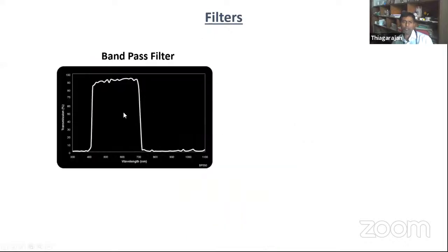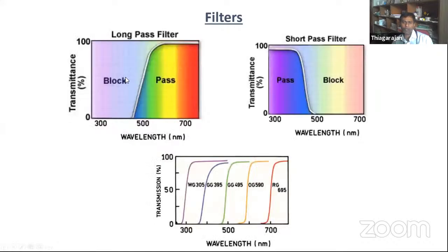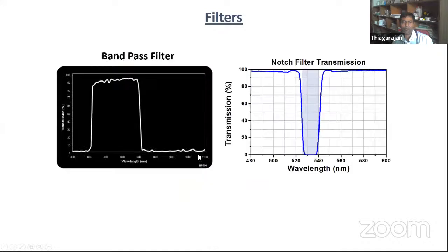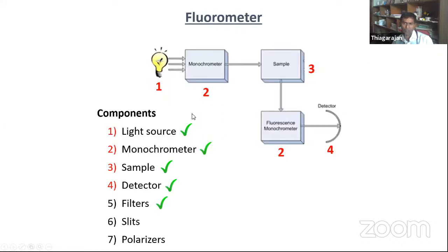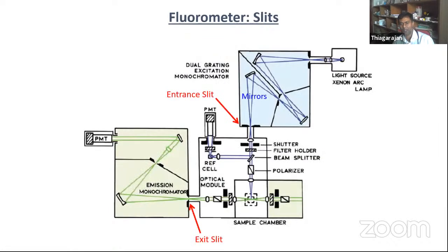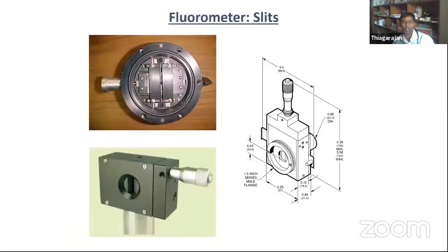This is the band pass filter. Long pass filters pass everything above a cutoff. In the case of a band pass filter, it passes only a certain band. It passes only 400 to 700 nanometer. Below or above, it cuts everything. So we can use filters to remove the second order pattern or Rayleigh scattering from the solution.